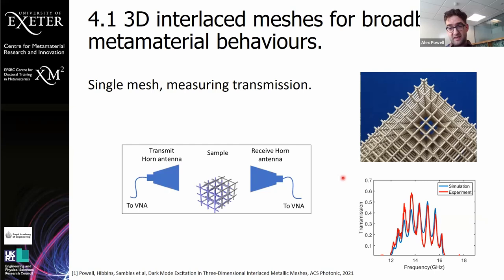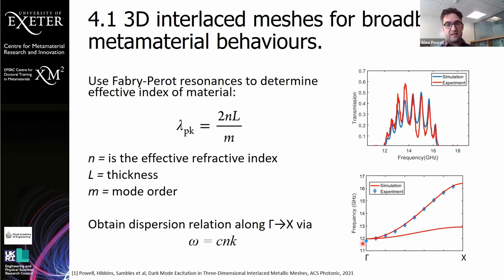And we can see the envelope, which we expect due to the dispersion relation of this. And we also see these Fabry-Perot peaks, which are due to reflections from the front and back surface interfering and causing standing waves in the sample. These are actually quite useful because we can use the Fabry-Perot resonances to determine the effective index of the material for different wave vectors.